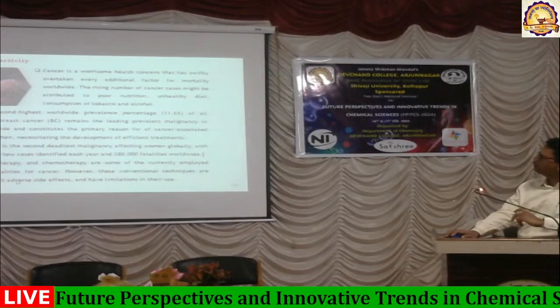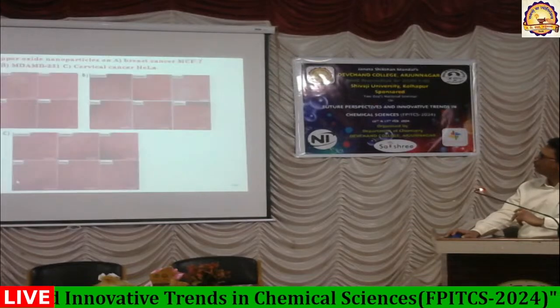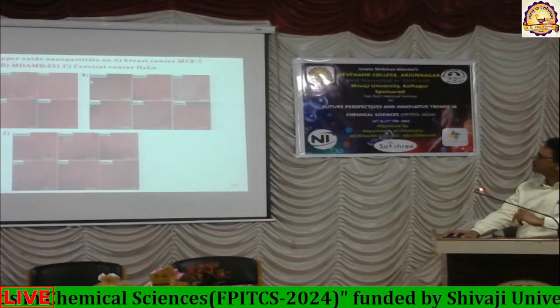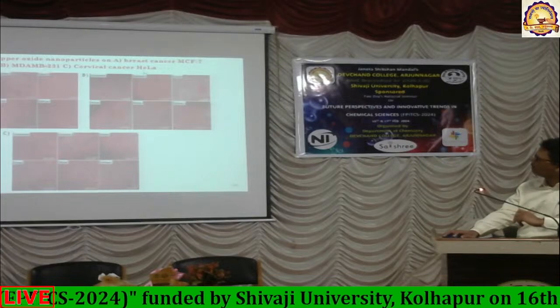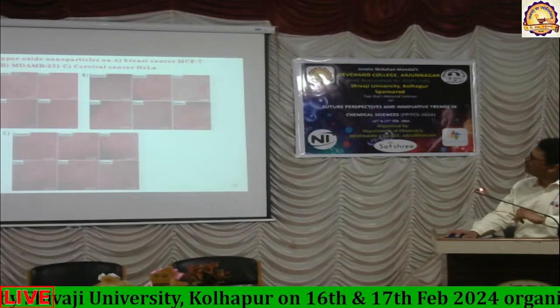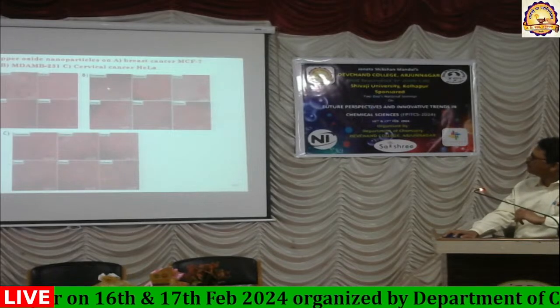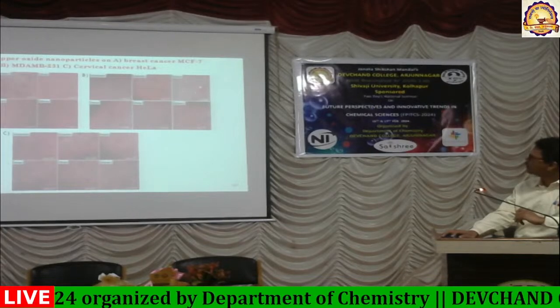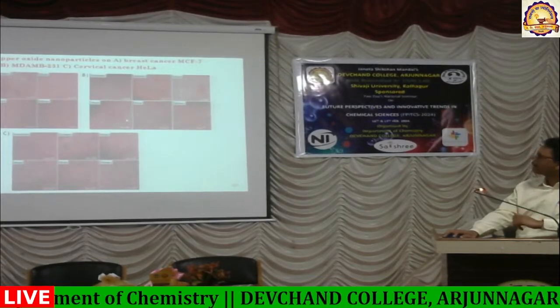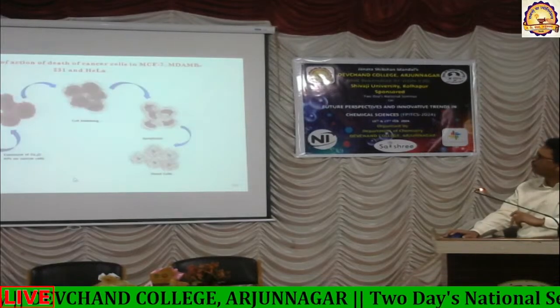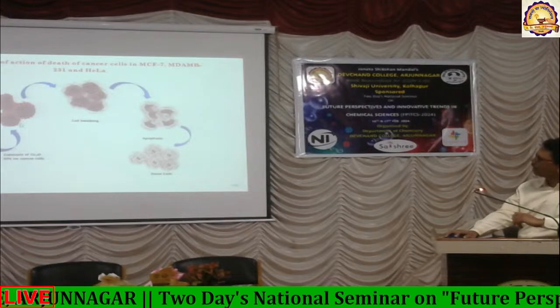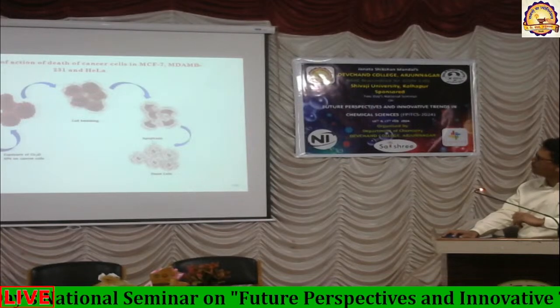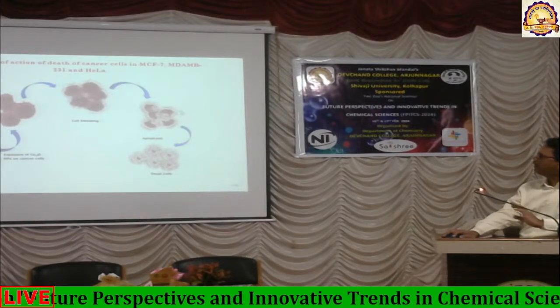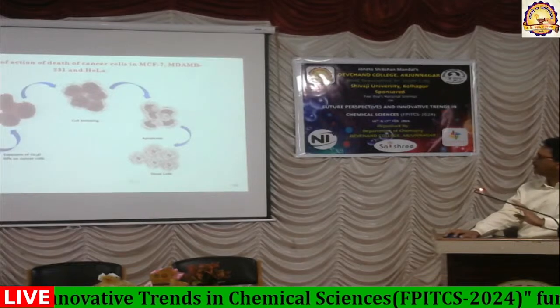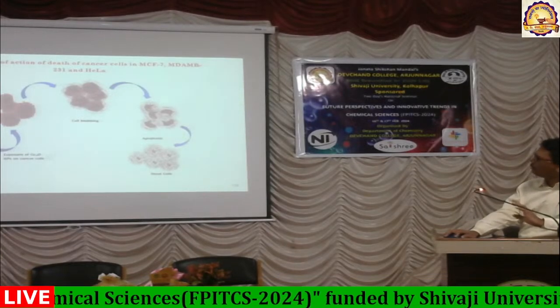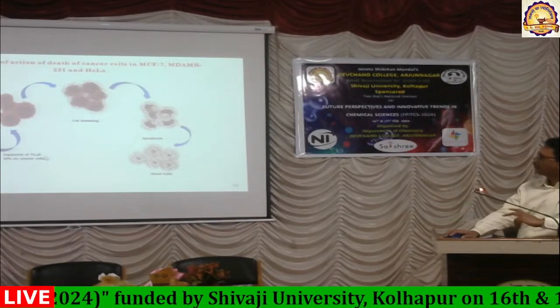Okay. So these copper nanoparticles, as I told you, also act against breast cancer, MDA, and cervical cancer, where the clear zones indicate inhibition. This first square is untreated, and these clear squares indicate that the anti-cancer activity has taken place. And this is a mechanism where, on exposure to the copper oxide nanoparticle, cell shrinkage and chromatin condensation will occur, and apoptosis will occur, because it is a programmed cell death, where the anti-cancer property can easily be observed in the dead cell. So programmed cell death can occur with exposure to the copper oxide nanoparticle.